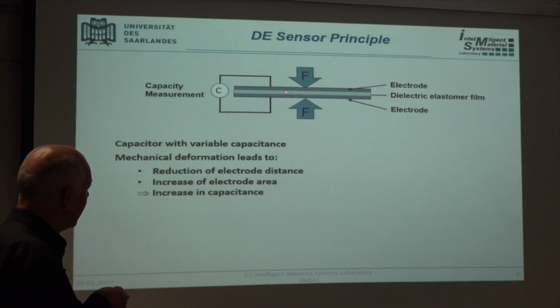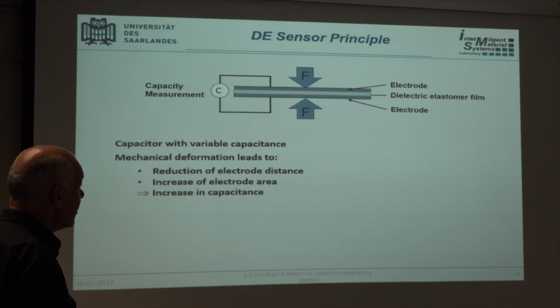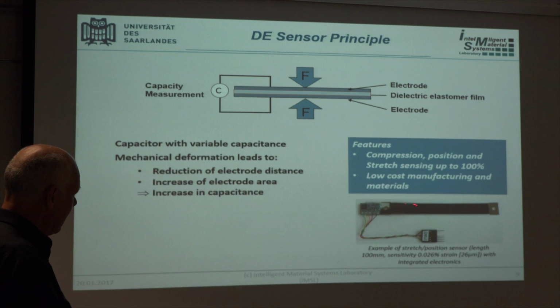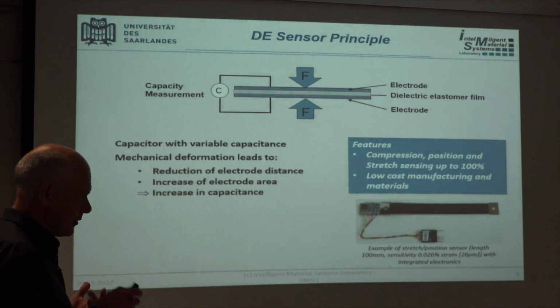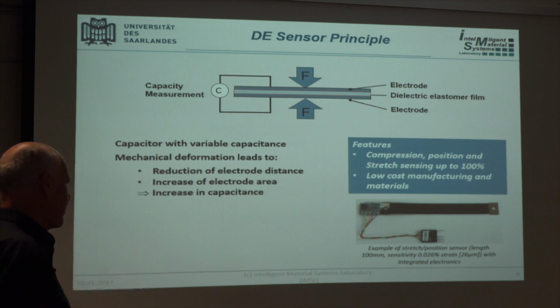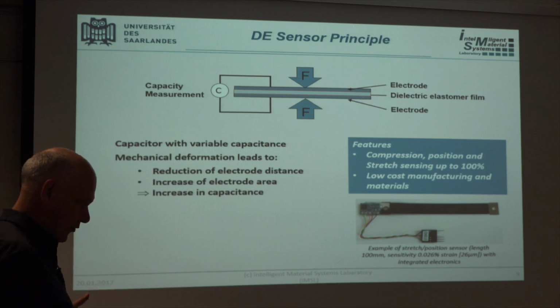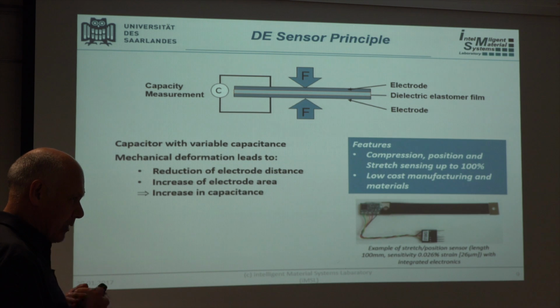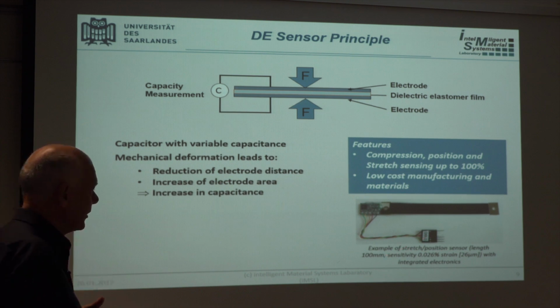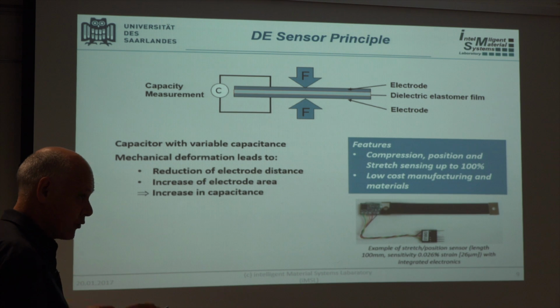How it works, you just deform it mechanically and you change the capacitance of this capacitor, and basically you can correlate the change in capacitance to a number of interesting physical quantities like deformation, stretch, pressure, and this is something that can also be made in a very similar way from a silicone membrane and electrodes, and you can add electronics to read out the capacitance change. You can come up with very interesting sensors that have properties that you don't find very quickly with other sensors, because you have very large deformation capabilities and still a very high and accurate readout. Here's an example of a sensor that has a length of 100 millimeters, but it can read down to several micrometers, even though you can deform it up to almost 100%.